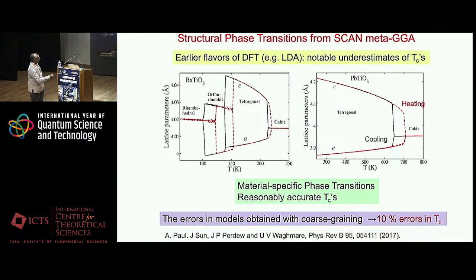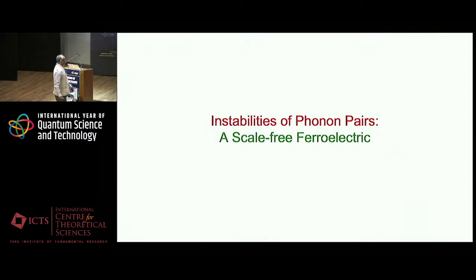And not only that, you see the contrast between lead titanate and barium titanate. Here you have 3 phase transitions. By the way, the 2 sets of lines are associated with heating and cooling simulations. These are all first order phase transitions, and associated with that is the hysteresis. So this is really, I feel, a truly remarkable success of a quantum-based approach to predict these transitions with reasonable accuracy. So instabilities are important ingredients we access using DFT.